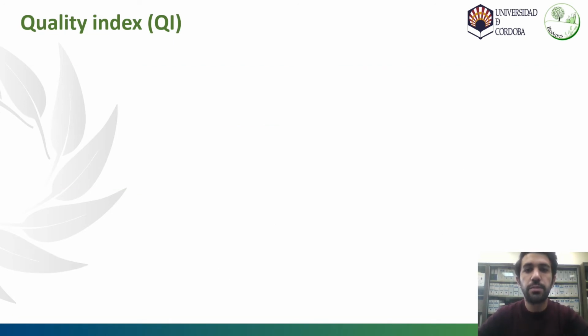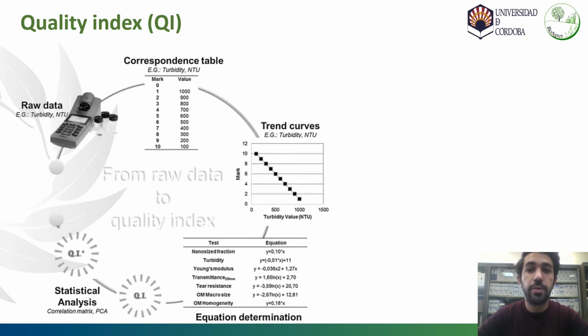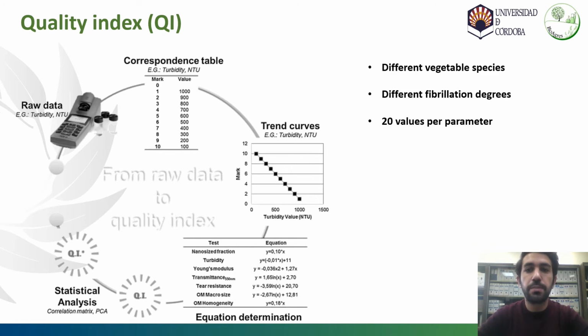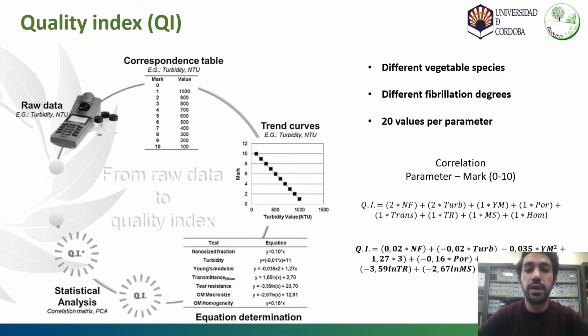In this index, to determine the transformation of the value of each variable to a scale from 0 to 10, nanocelluloses were obtained from different passes using a so-called ultrafine grinder, collecting samples every 20 minutes to obtain different degrees of fibrillation for each sample. A total of 20 values per property were taken to define in a proper way the correlation between the property and the fibrillation. With this correlation, lines for each property were obtained and a value between 0 and 10 was given, which will be used for extrapolation of this value when obtaining the result of this analysis.